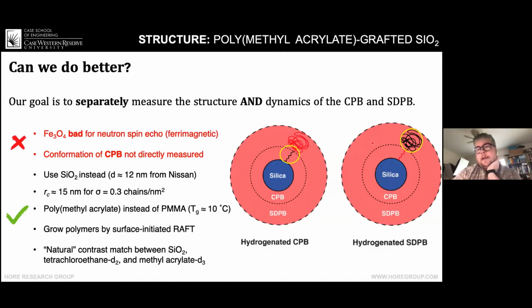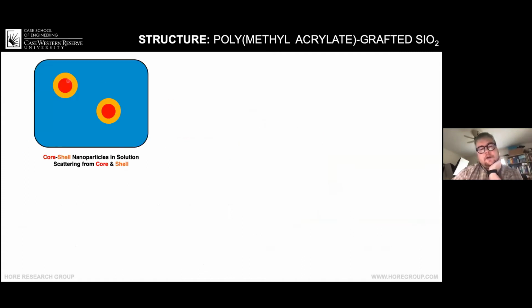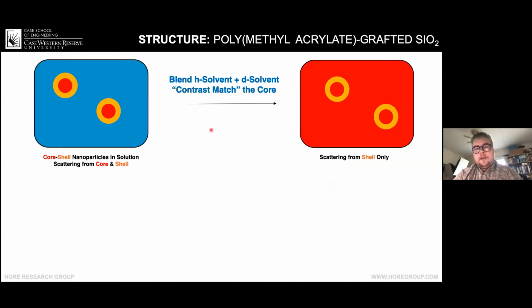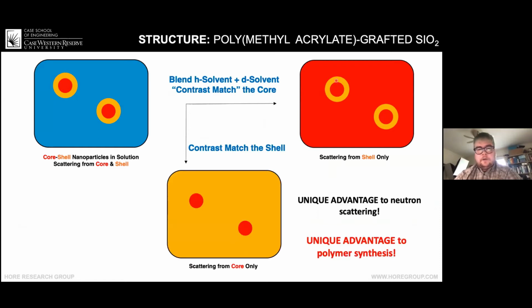So what I mean by that is if you look at these nanoparticles here, the red is the core of the particle, and the yellow is the polymer brush, and the blue is the solvent. So by mixing together different ratios of deuterated and hydrogenated solvent, we can, for example, hide the core and only scatter from the brush. Or if we contrast match the shell by using a different mixture of hydrogenated and deuterated solvent, we could only scatter from the core. So this is a huge advantage for neutron scattering.